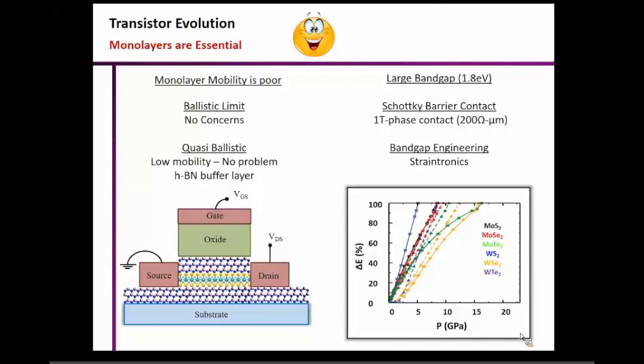But then there is a lot of recent work where you can actually do some phase engineering, and you can transform in the contact area this 2D material from 2H phase to 1T phase, and that has shown to give you contact resistance of the order of 200 ohm micrometer, and that number is pretty reasonable for even state-of-the-art silicon technology. Okay? So this number is really competitive with that number. But that's not the only thing.